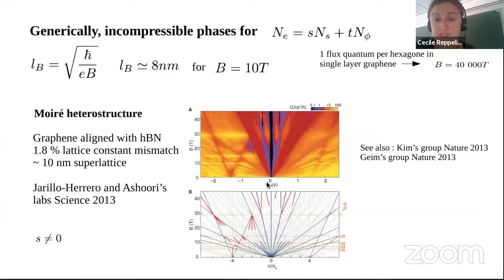Here, the unit is the gate tension, which is what allows you to actually change that density in the sample. I have here my usual Landau levels, basically those lines that cross the y-axis at zero field. This is just the typical quantum Hall effect, but you see, for example, around here or around there, that there are other lines, for example this one or that one, that correspond to a non-zero S. So you start exploring the full possibilities of the combination of lattice and magnetic field.